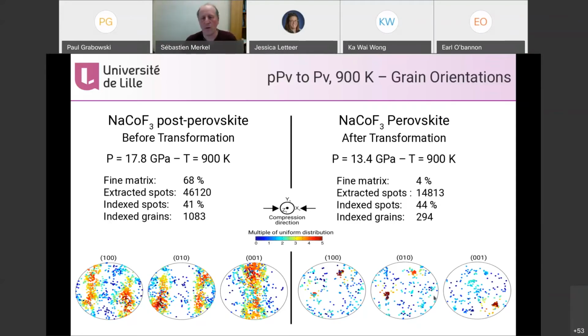So what I think we're forming when we go back to perovskite, we're not forming many grains of perovskite, we're actually forming one big grain with many twin domains. I don't know why, but it's very different from when you go up in pressure. When you go up, it's actually a martensitic transformation with orientation relationships. When you go down, it's a diffusive transformation with complete reconstruction of the microstructure.